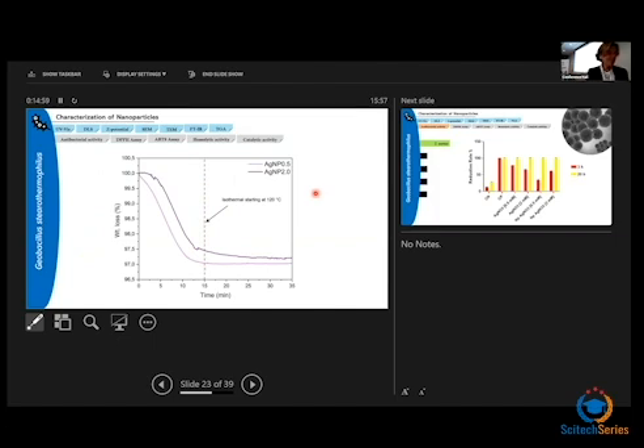The isothermal gravimetric analysis was therefore employed to evaluate the thermal stability of the nanoparticles synthesized starting from 0.5 and 2 millimolar precursor, and the thermograms revealed a minimum weight loss during the initial phase. Upon reaching the isothermal phase at 120 degrees, the weight loss stabilized, suggesting the absence of further thermal degradation or any significant mass loss, confirming the thermal stability of both formulations, which can be ascribed to the presence of robust, thermostable biomolecules in the coating of these nanoparticles deriving from the extremophilic microorganisms.